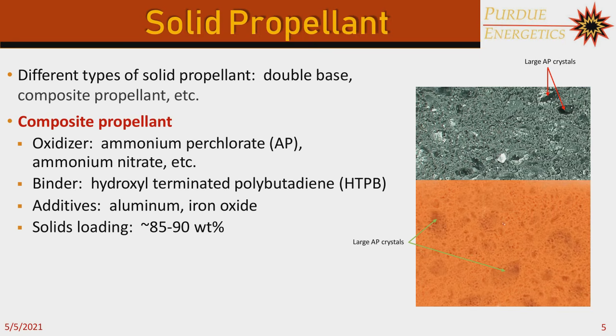So ammonium perchlorate is a very commonly used oxidizer in composite solid propellant and typically makes up the majority of your solids loading. You can also include other particle additives such as aluminum, iron oxide, or others, and typically you add them to help improve the burning rate of these propellants by either raising the flame temperature or lowering the decomposition temperature of ammonium perchlorate. And typically, when you combine the oxidizer and the additives, that can make up about 85 or higher solids loading or weight percent in your mixture.